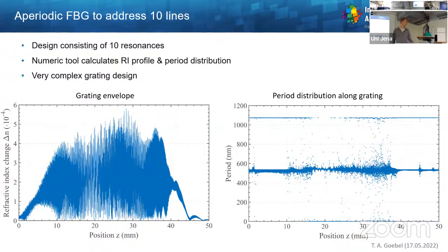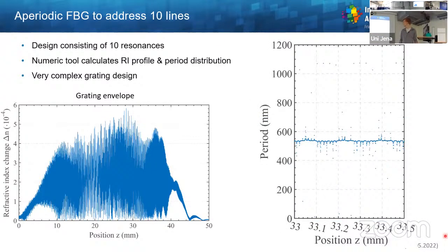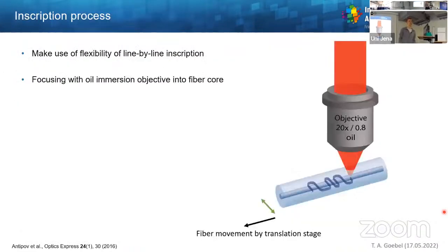So let's have a look at a magnification. You can see that there is no regular pattern at all, and it's very challenging to realize this structure. But luckily there is one technique, the so-called line-by-line technique, which gives us the advantage of being very flexible. We use femtosecond focusing with the objective and focus our laser beam into our fiber core. Now, like drawing with a pen, we can adapt the period very flexibly by moving the fiber underneath the laser beam in a rectangular pattern. This gives us the flexibility of completely freely choosing the period.